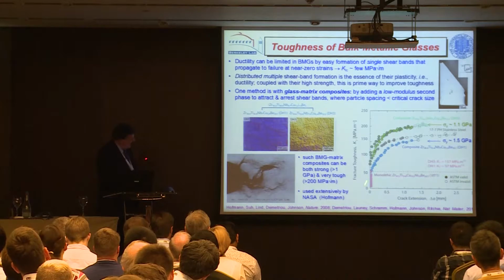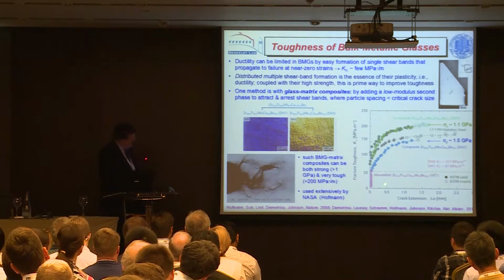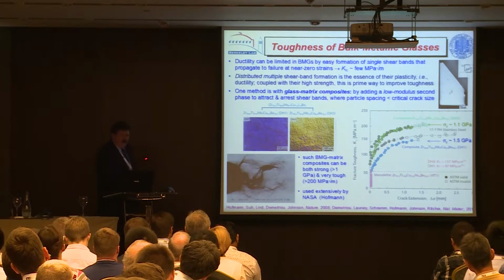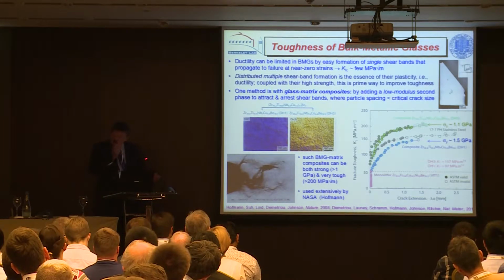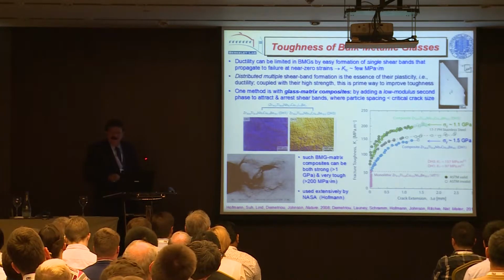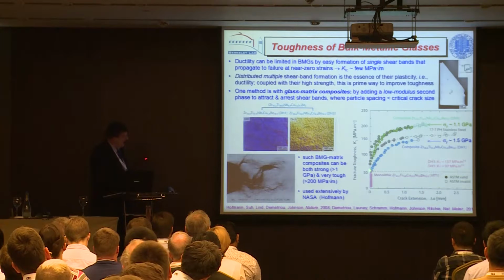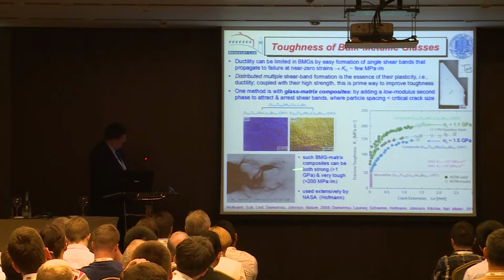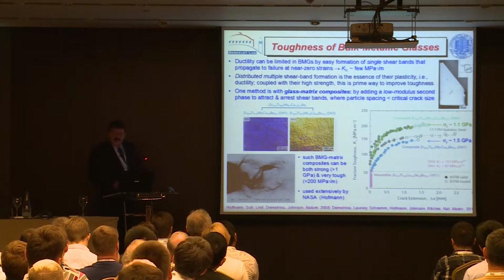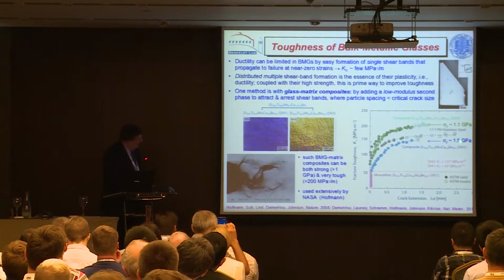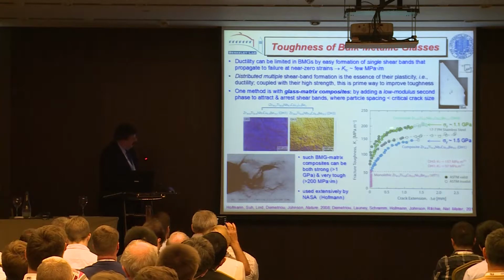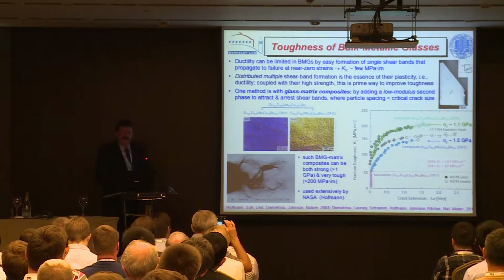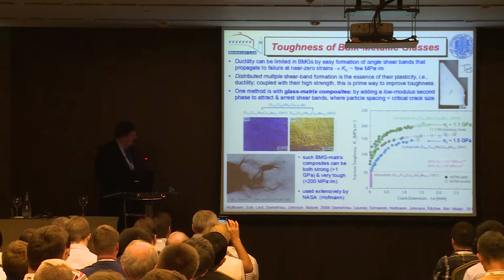The typical glass, this is Vitreloy, the first ones that came out. It has a toughness of 50 and then it breaks catastrophically. A lot of golf clubs were made of that, and a lot of golf clubs fractured catastrophically. But these ones show very strong R-curve behavior. This image here was one of these glass composites, and we're getting toughnesses of around 200 at the best with strengths over a gigapascal. These are very respectable.